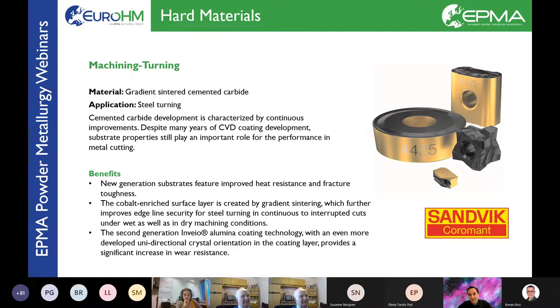And you see here, these colors actually are not painted. It's not powder. It's just that the different phases, when we are making a carbon nitride or aluminum oxide, will have different colors, and we can create these kind of fancy structures and eventually change also the colors to more attractive ones. So I would say it's a nice example of a very complex microstructure on cemented carbide, and also the combination with the coating to achieve certain properties. And you know that in this type of machining, and especially turning in steel, is probably one of the most widespread applications and largest volume of carbide we are producing basically in Sandvik Coromant. So I think that is my few words to this.